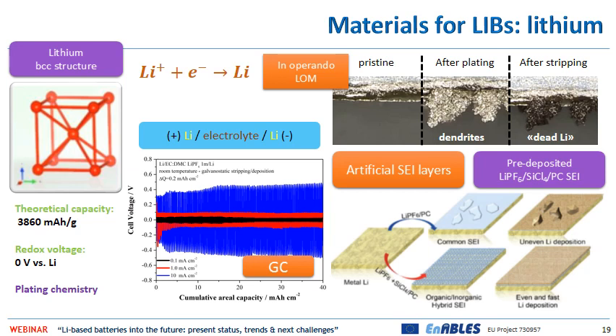This formation and dissolution occurs through the formation of dendrites. These dendrites grow during plating and are stripped back during the stripping. Again, like in the case of graphite, the main problem is the fact that at such a very low potential of the operation of lithium, the electrolyte is degrading on the surface of these dendrites, and so after stripping, there's an empty shell of SEI layer, called dead lithium, that is left behind the old dendrites. This dead lithium is accumulating cycle by cycle and obviously leads to the deterioration of the performances.